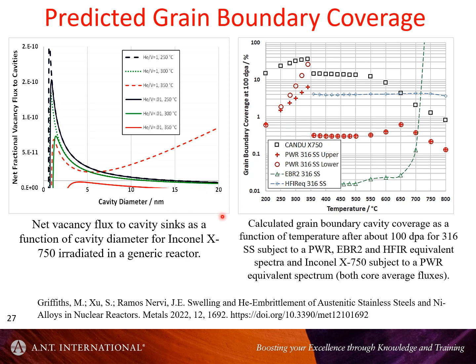So we've found that when you look at the measurements of the helium bubble production, you can deduce how the sink strength changes. And the temperature dependence, the sink strength in the matrix, it's actually decreasing with increasing temperature for a given amount of helium. It's smaller at the higher temperatures, and that's because the bubbles themselves are much bigger. And for various reasons, one then sees as a function of temperature, if we consider bubbles alone, we get an increase in the coverage with increasing temperature.